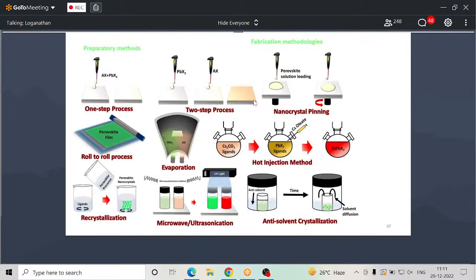You'll have very good fun in your laboratory, but the problem is you have to control your stability as well. So it's good. You can prepare the perovskites in different ways, like one-step process, two-step process. These are the precursors they use, and then they heat and anneal them to form very good quality thin films. They can also use nanocrystal pinning techniques, in which they use some polymer to pin them. Then they can reduce the defects. And there are the hot injection method, evaporation, roll-to-roll process, recrystallization. So there are many ways to fabricate.